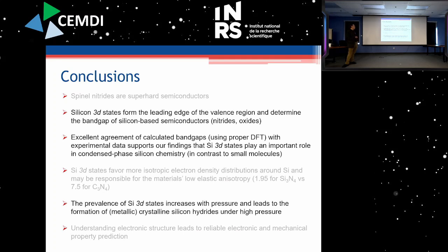So just to conclude on that part, we saw that the silicon 3D states are very important in the bonding topology and the valence region of silicon-based semiconductors, whether it's nitride, oxides, and hydrides under high pressure. Our DFT calculations reproduce structural properties. I didn't discuss that, but they do reproduce known experimental structural properties very well, and even the electronic properties such as the calculated band gaps. We just need to use the proper model to do that. And so the 3D states certainly play an important role in condensed phase silicon chemistry.